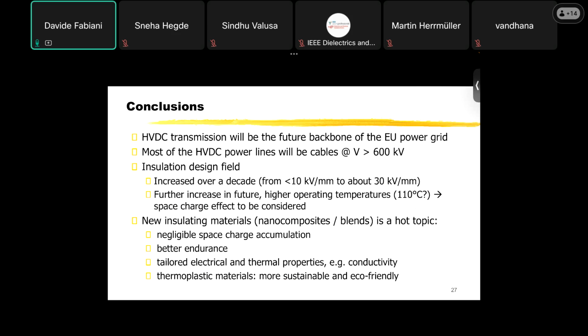Now it was less than 10 kilovolts per millimeter some years ago, and now cable companies want to exceed 30 kilovolts per millimeter. This further increase also will be in operating temperature. The cable company wants to exceed 90 degrees, go perhaps to 110. And of course, space charge could be a problem in that case.